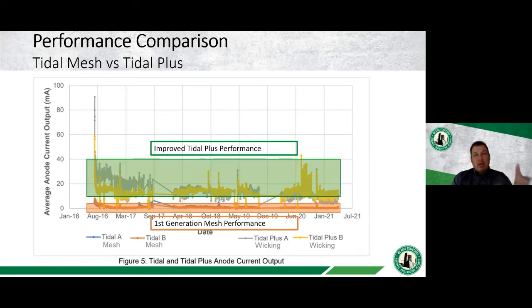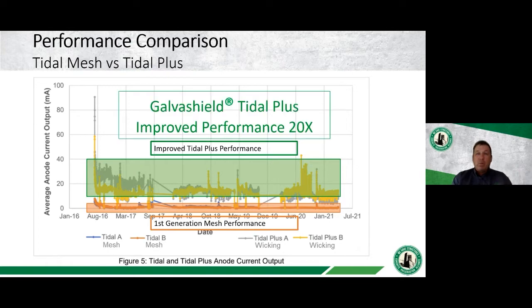And if we come in and look at the Tidal Plus version of it, you can see that we've actually got quite a bit more current off of basically the same type of length of jacket. So what did we get out of it? We can get anywhere from 10 to 20 times the amount of current output from these jackets. A big reason for that is because we're able to move that salt water up into the higher elevations of these wicking anodes and get better performance and better utilization out of it.